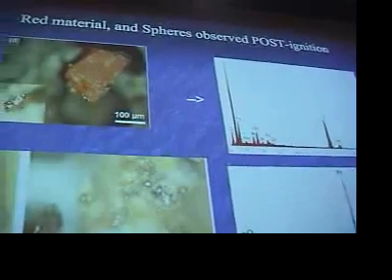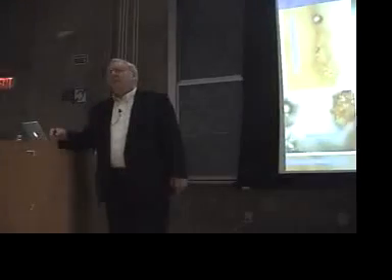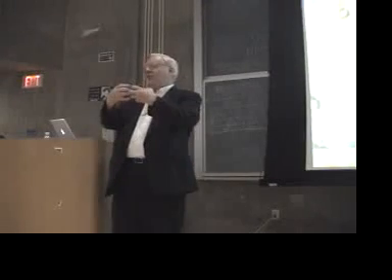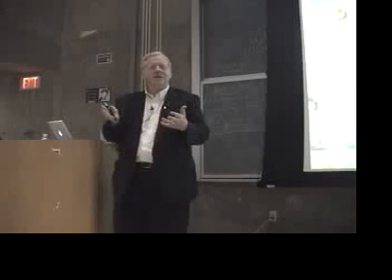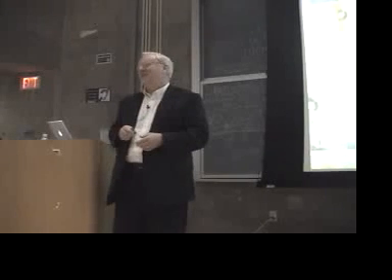So as we soak this in this paint solvent, we've got regions of iron oxide, see the oxygen peak there, it's enormous. Iron oxide, and then other regions of aluminum-rich and silicon-rich in different regions. By the way, separating the aluminum from the silicon like that means this is not an aluminosilicate. Paint solvent does not reduce aluminum. It doesn't make aluminum out of aluminum oxide or out of aluminosilicates.